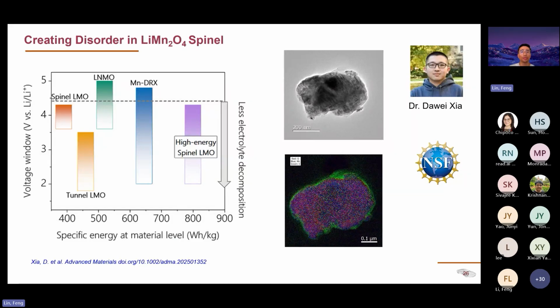So Dawei Xia, who recently graduated, started looking into manganese-rich cathodes. He started with a spinel, which is a commercially available material. Spinel is a very good material in that it contains only manganese, which can be domestically sourced very easily. Well, at least we have a lot of manganese minerals in the United States. Traditionally, if you use the spinel, the operating voltage is roughly around 3.6 to 4.2, 4.3 volt, and the specific energy at the materials level is around 400 watt-hour per kg.